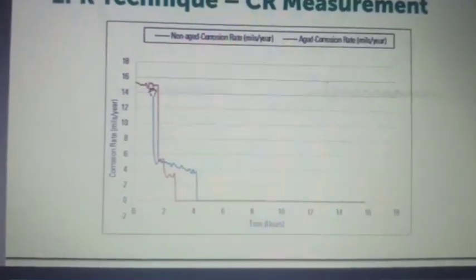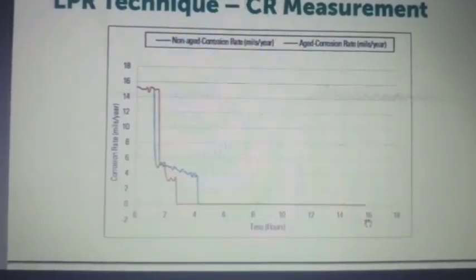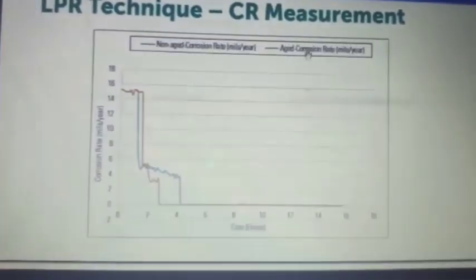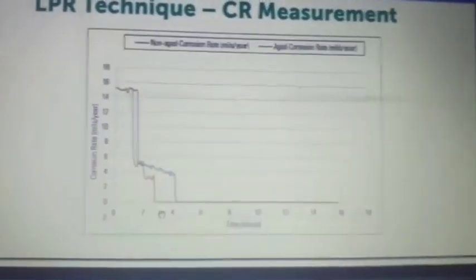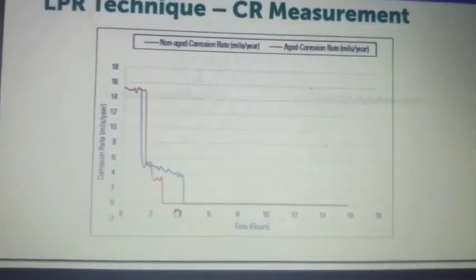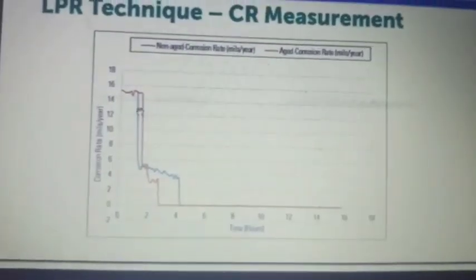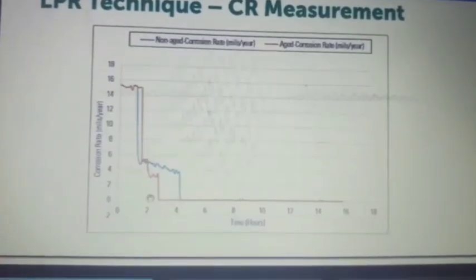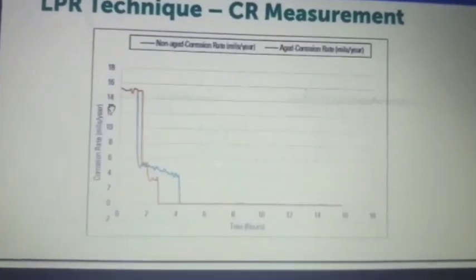Once I start introducing that corrosion inhibitor, you see the corrosion inhibitor starts functioning, and after some time the corrosion rate drops. For the non-aged corrosion inhibitor, it takes 4 hours, and for the aged corrosion inhibitor, it takes 2 to 2.5 hours. We will not go into what is non-aged or aged, that is a different issue. But what I'm saying is, you can directly see the corrosion rate in mils per year. This is the advantage of the LPR technique.